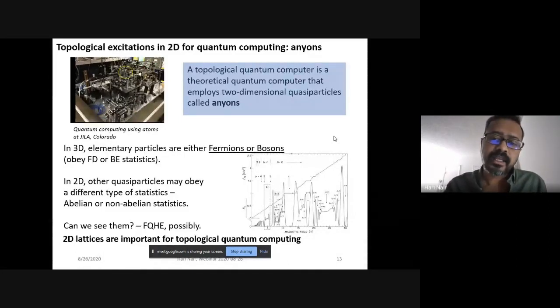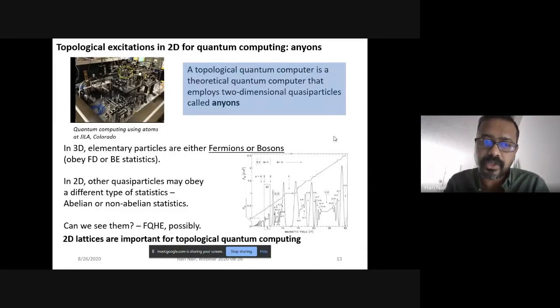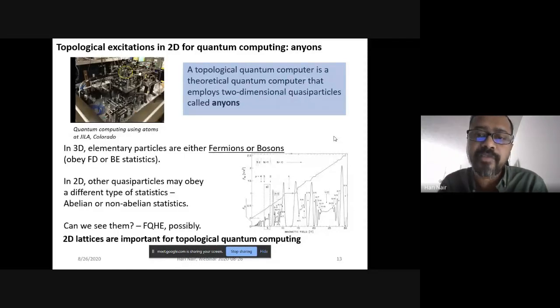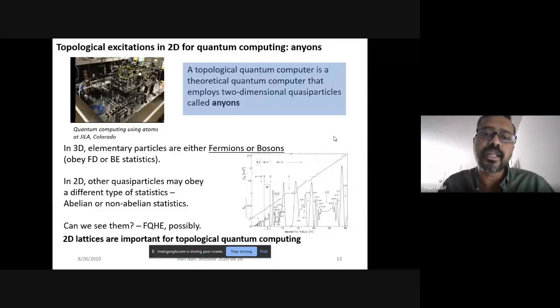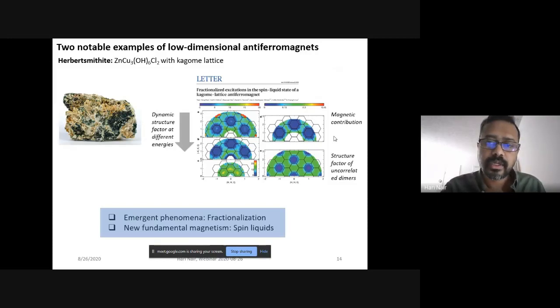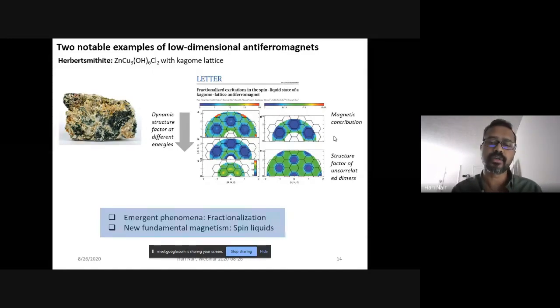It means that the electrons are the constituents in that material, but they show some interesting properties when those electrons form a quasi-particle with a fractional value, because we don't really see a half of an electron. But electrons somehow bind together in a quasi-particle, and they can behave like a particle with 1/3 of an electron, with 1/5 of an electron. And that is a fractional excitation. In this compound, people used neutron scattering, which is an experimental tool I also use, and they found a magnetic contribution, and they could explain the excitations only based on fractionalized charges. And that is one of the connections that I wanted to make.